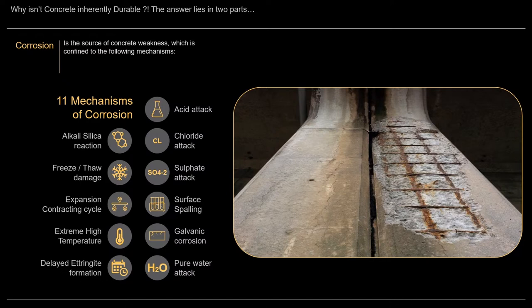surface. Delayed ettringite formation. Ettringite is a normal, natural part of the cement matrix. It's actually a very useful product of hydration. But when concrete is superheated, when it's being formed perhaps in steam curing situations and what have you, if the ettringite doesn't get a chance to form naturally before the concrete hardens, but if it subsequently gets wet, it can cause expansion and cracking. Acid attack is another one. Acids will attack, will etch many, many things, including steel. But on the surface of concrete, it's not just the surface that's going to get affected. If the acid gets drawn in by suction into the concrete, it can damage it at depth. It can also lower the resistivity that you get around the reinforcement and the nice alkaline environment that normally exists.